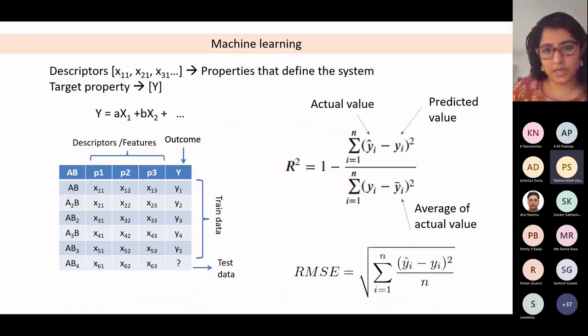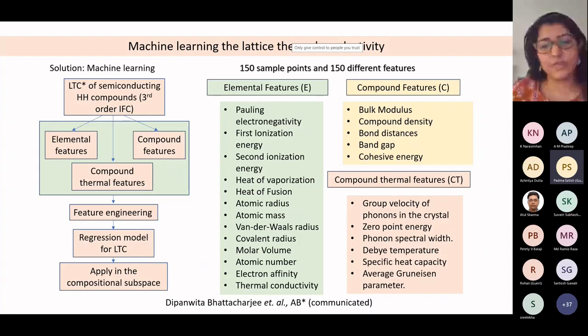So therefore, we proposed a machine learning model. I will just briefly introduce that. In this case, we first have to have some calculations which have been done. Either calculations or experimental results, both can be used. In our case, it is the first principles calculations which we have performed for as many systems as possible. Once we build the model, then depending upon the model, we can predict the lattice thermal conductivity of many other materials which fall into the same class. So I will show you very briefly.